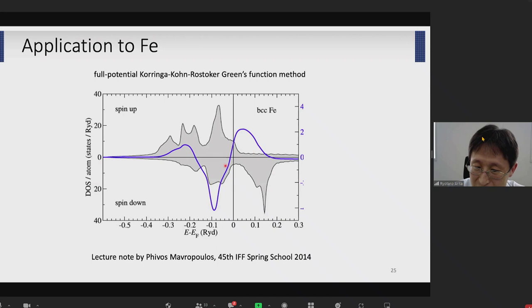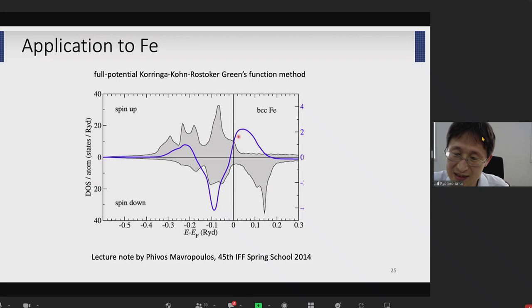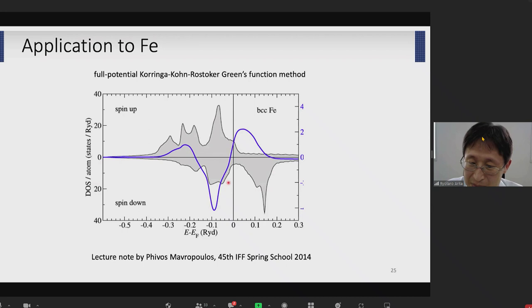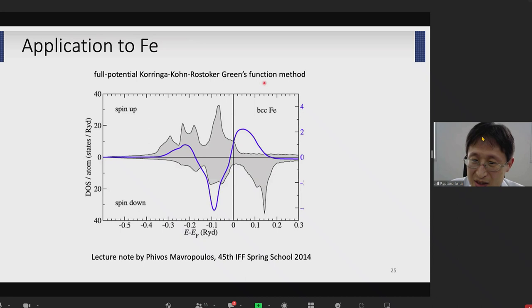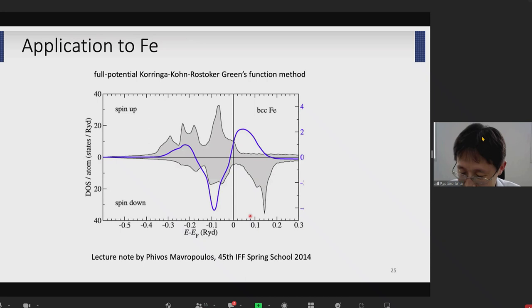If we dope holes — corresponding to manganese, chromium, and so on — these transition metals tend to be antiferromagnets, which is also consistent with experiment. This curve qualitatively explains why chromium and manganese tend to be antiferromagnets, why cobalt has a higher Curie temperature than iron, and why TC of nickel is lower than that of iron or cobalt.